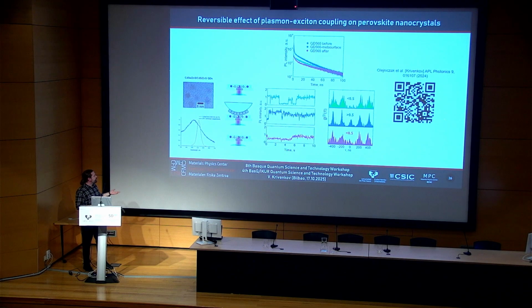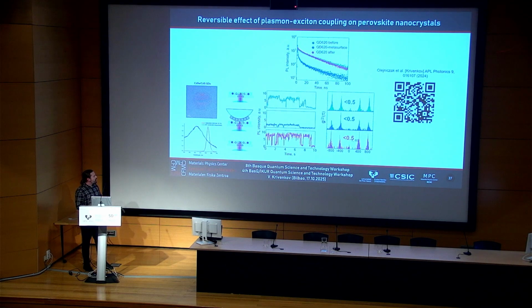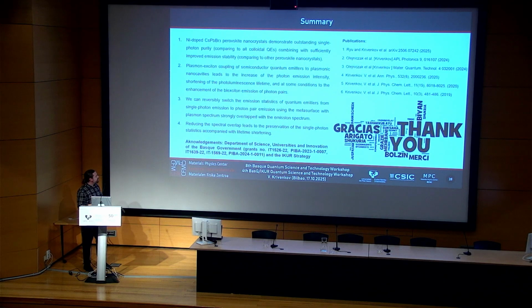Also, we could achieve the situation where we conserve the single photon purity of the quantum dot coupled to the plasmonic particles, and at the same time compress the lifetime. For that, we needed to shift the emission spectrum of the quantum dot out of the maximum of the plasmonic band. But this situation we experimentally achieved. So this is most of the results which we achieved in the last years.